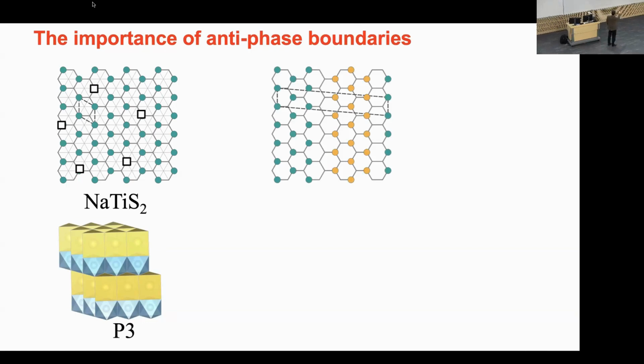This is something that you can calculate with DFT. So this is a periodic unit cell. So a structure like this, instead of having vacancies uniformly distributed, what it would rather do is have the vacancies coalesce at antiphase boundaries. So here, and then you have perfect ordering. So you don't have these isolated vacancies. Instead, you have all the vacancies coalesce at these antiphase boundaries, where you have perfect ordering. So it's filled, empty, empty. And normally you'd expect the filled one, but that's where the vacancy is. But instead of then continuing with empty, filled, now you form a perfect ordering also of sodium, but shifted to the other sublattice. So you kind of create an extended antiphase boundary. And here is another antiphase boundary of a different type, but it's the similar kind of concept. So you have these antiphase boundaries. And this is the type of supercells that you can calculate with DFT.